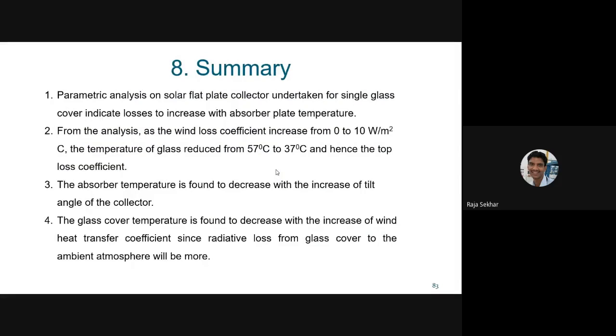So coming to the summary of all this work. The parametric analysis has been undertaken, and the performance of this collector has been studied for different plate temperature, and from the analysis, as the wind loss coefficient increases from 0 to 10, the glass temperature reduces from 57°C to 37°C, wherein you can reduce the different types of losses happening in the collector. And the absorber temperature is found to decrease with the increase of tilt angle. As I said, from 20 to 80 we have changed. So as the tilt angle of the collector increases, the absorber plate temperature has been found to decrease. So that means the intensity of radiation falling on the collector has reduced.